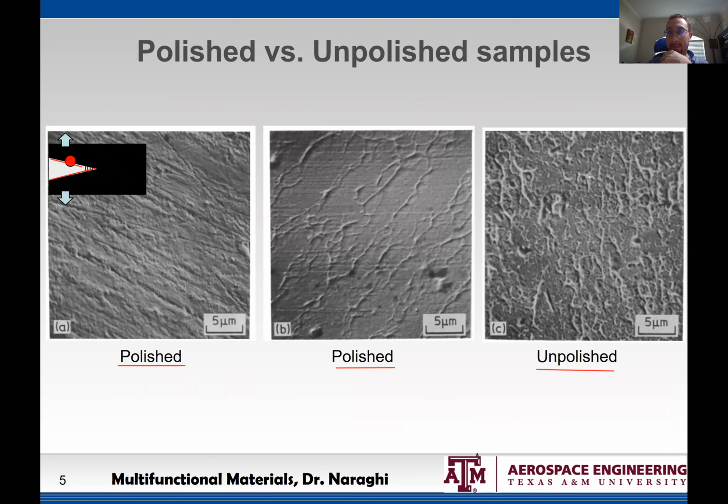Imagine all these roughnesses you see are parts of the craze that eventually, when the crack opened up, completely snapped. The polymer chains snapped. So this is when the crack opened up, and now I'm looking at this surface, where the crazes used to be. I'm going to stop this video, and we will continue in the next video. Thank you.